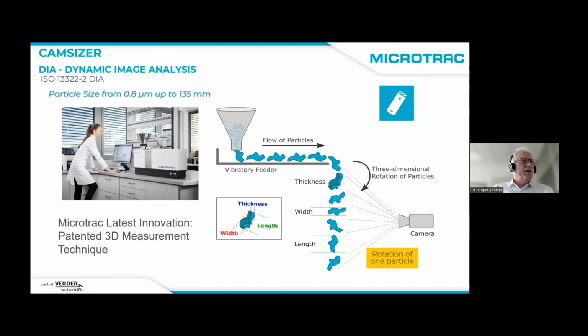Another system, a pure dynamic image analysis machine, is the CamSizer series. So in the series, we can work depending on the equipment, determine particle sizes in the range from 0.8 micrometers up to 135 millimeters. The latest innovation, we had a patented 3D measurement technique where particles flow, for example, over a vibratory feeder and then fall down, and along the trajectory with the camera, we can see and follow all the various movements of the particles and then get an idea also of their three-dimensional morphologies.